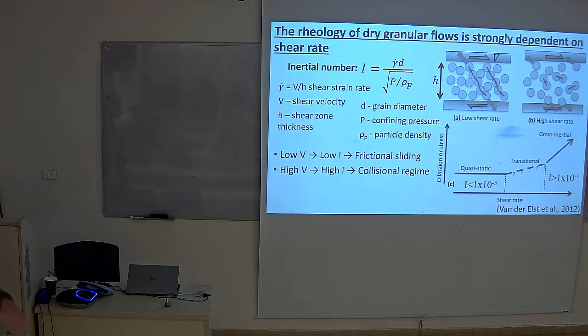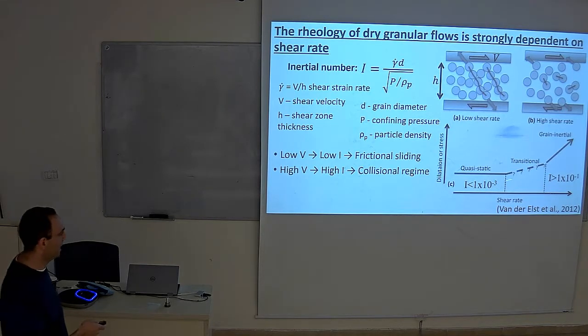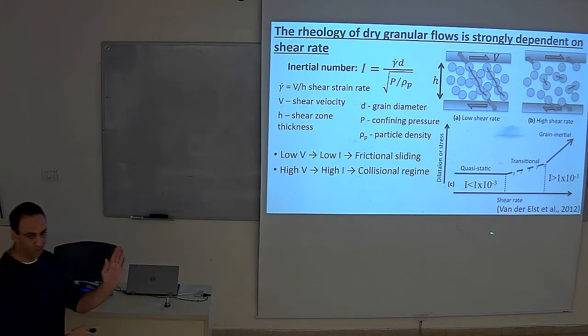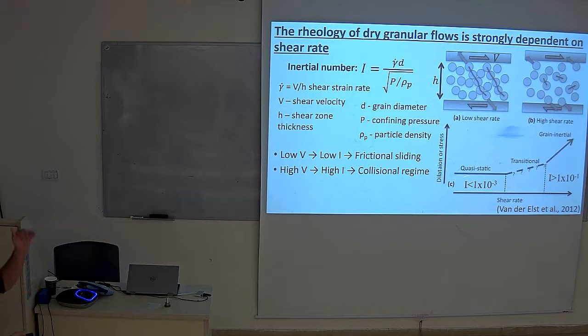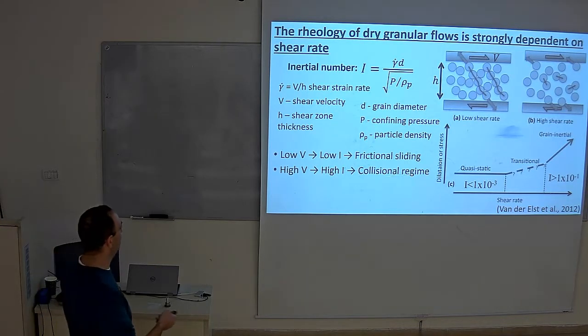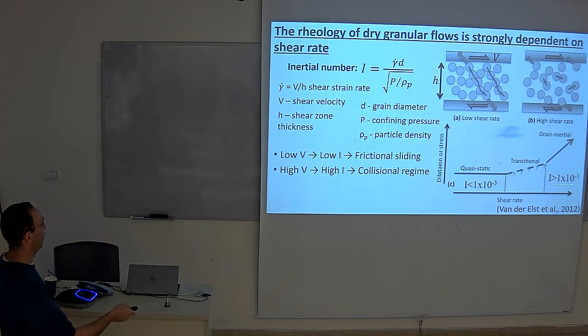So looking at the results about what we know about the different regimes, this is the dilation, how it's moving up and down, and this is the normal stress on the system versus the shear rate. For very low velocity, and very low inertial numbers, lower than 10 to the minus 3, we're getting the quasi-static regime, where when we are moving between velocities, there is no change in the dilation. It's still the same volume of the material. However, when we are getting to the grain inertial regime, we are getting dilation or increasing of stress on the particles. So these are the different regimes, and these are the numbers of where they exist.